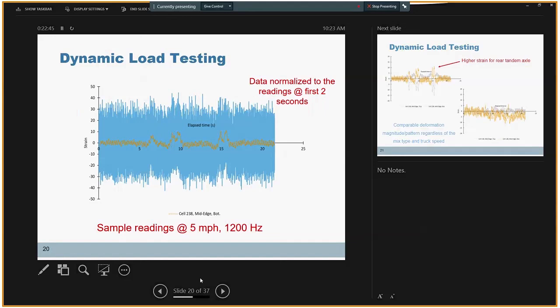Also, these pavements were exposed to controlled traffic loading. An 18-wheel semi-tractor trailer of MnROAD was used to load the pavements, and data was gathered using a data acquisition system at 1200 Hz frequency. Readings were done at 2 speed levels of 5 and 35 miles per hour. And here I have a sample graph.